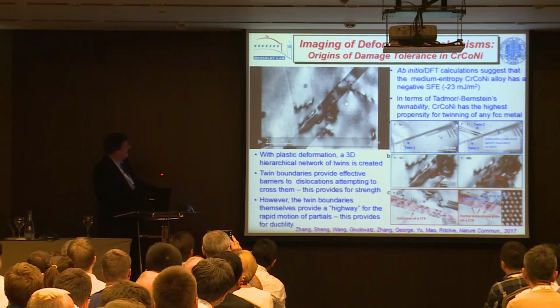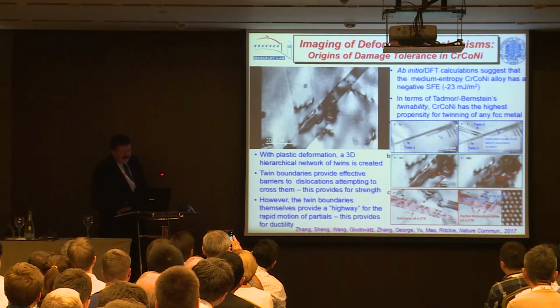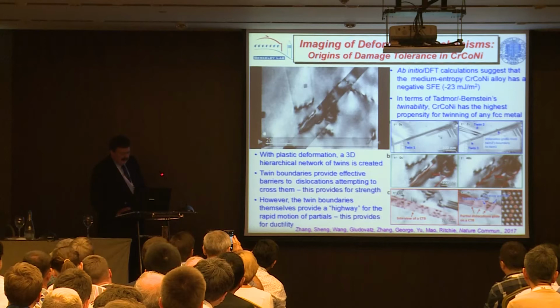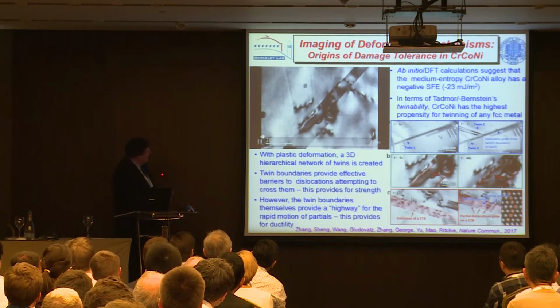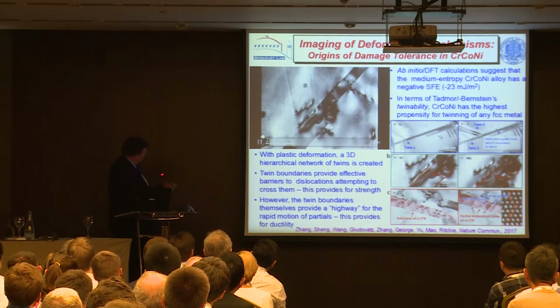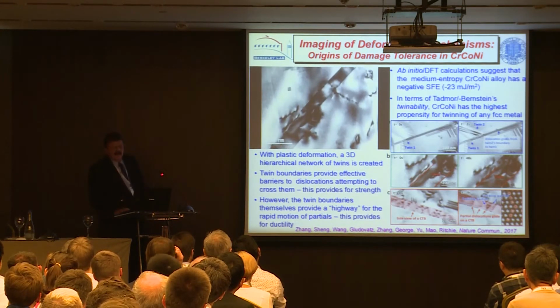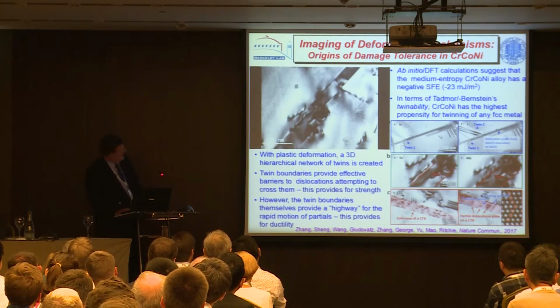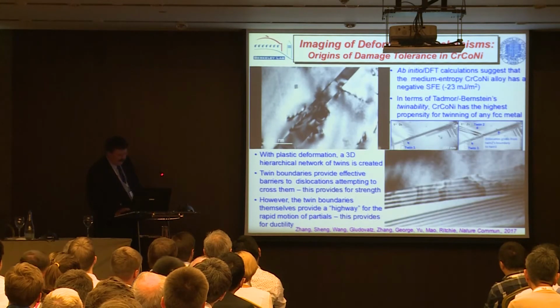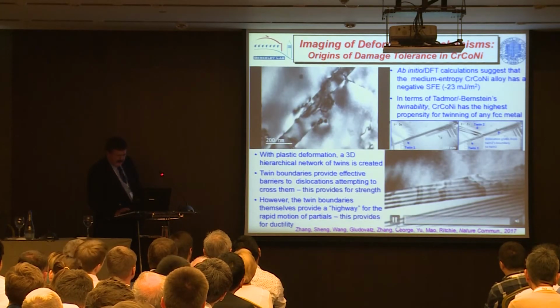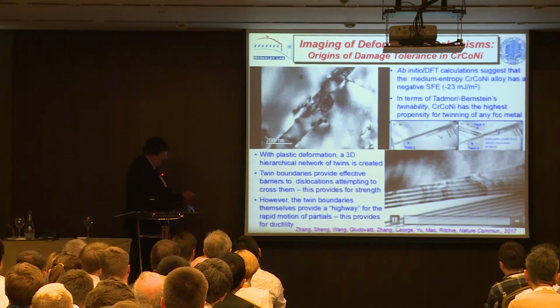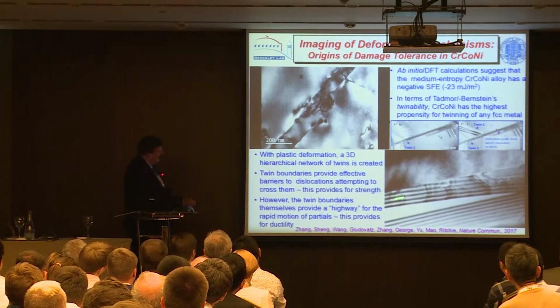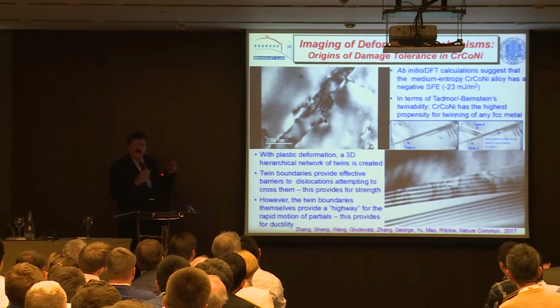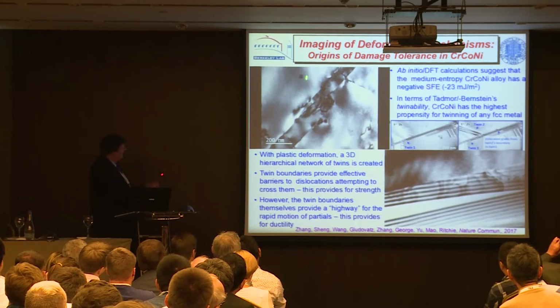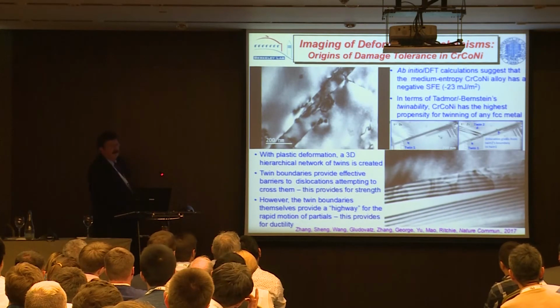There's a twin structure throughout. The twin boundaries will effectively arrest dislocation motion. You can see one coming up here. But the boundaries also are highways by which dislocations can move fairly fast. This is basically looking at a twin boundary, and you can see these dislocations moving along the twin boundary quite rapidly. Again, we have a duality of mechanisms: arrest of dislocation motion and rapid motion.